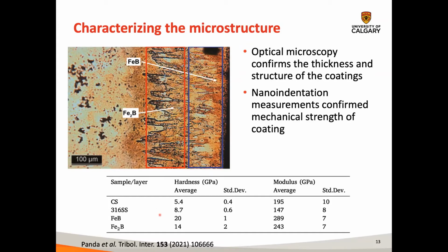And what you see here is the carbon steel base layer hardness, and this is the hardness of the stainless steel. So stainless steel is a bit harder, that imparts more wear resistance, but you can see there's approximately a 2-fold improvement in hardness from the stainless steel to the boronized steel. And so you really see an enhancement of the wear performance of these coatings from this improved hardness.